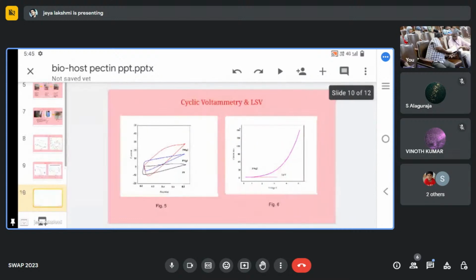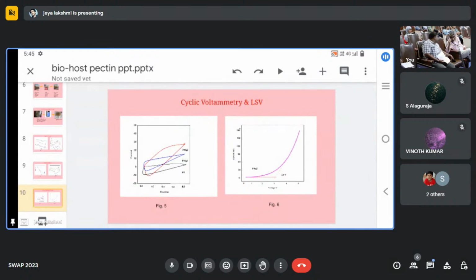Then we move to the cyclic voltammetry and LSV. In CV, we have a distinct anodic oxidation at the electrode interface. And next we move to the LSV, which is another important study, showing whether our electrolyte has electrochemical stability or not. From my samples, as I said previously in DSC, PMG2 has a high ionic conductivity. For that sample, I take the LSV. In LSV, it has been observed that the biopolymer electrolyte of PMG2 is stable at 3 volts, and it confirms that the electrolyte can be used for electrochemical